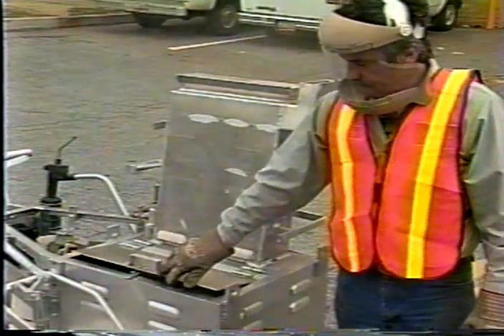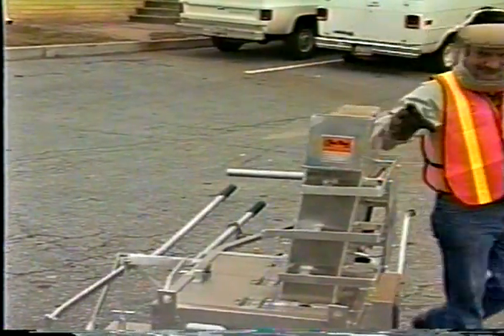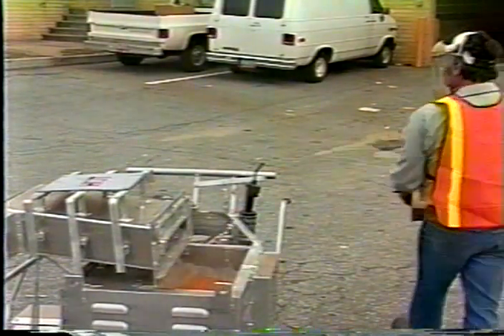Particular attention to safety should be given while loading materials into kettles. Always wear leather gloves. When opening a kettle lid, do it slowly. Preferably stand upwind from the applicator and slowly lift the lid to allow any fumes to escape before adding material. Always wear a face shield to minimize and avoid burns from splashing. Always carefully release bags or blocks of materials, letting them slide into the kettle. Never forcefully throw bags or blocks into the melter. The EPA-measured volatile organic compound, VOC content, of thermoplastic pavement marking fumes has been found to be negligible. By avoiding extreme concentrations which escape when a kettle is immediately opened, no discomfort should be experienced. Fumes emitted from melting thermoplastic do not contain any known carcinogens.